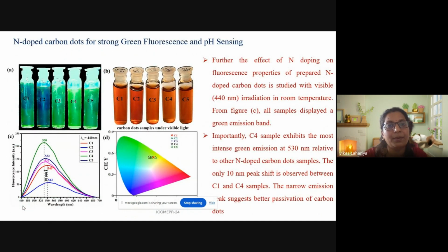Further, the prepared samples were examined by fluorescence spectroscopy using the UV chamber and the visible light. Figures A and B represent the carbon dot samples in daylight and in the UV chamber, and we can see that the C4 sample has an optimum amount of nitrogen, and it shows a highly bright, high-contrast green fluorescence when excited by the UV light. Figures C and D also represent the samples when excited by the 440 nm excitation.